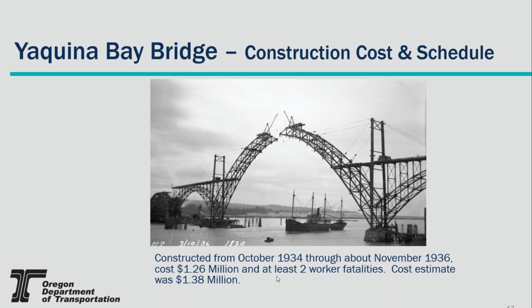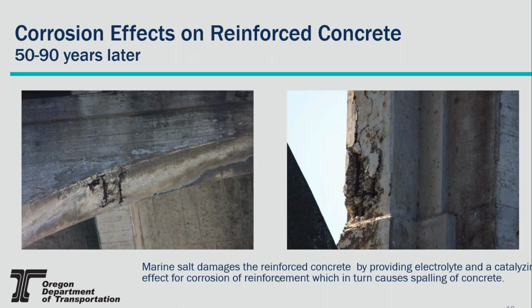So fast forward 50, 80, 90 years ahead, and you'll see a lot of things like these two photos. These bridges are all really close to the beach, and what you get is salt in fog, salt in wind, all pretty constant attack. The salt basically sets up a situation where the reinforced concrete has a ready electrolyte by way of the salt, and on top of that, the salt is also a catalyst for the corrosion, and the rebar corrodes and then spalls the concrete off, and then it turns into a spiral of badness.